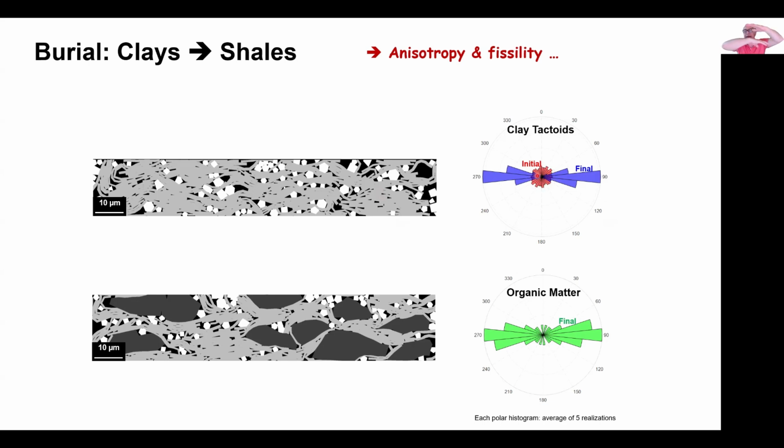But by the time they begin getting buried under zero lateral strain boundary conditions, the particles from random organization begin getting flatter and flatter, as you will see, in this case, probably simulating something like 1 megapascal. But I insist, this happens quite earlier on, like probably 10 meters in the subsurface. There is already quite a lot of particle alignment.